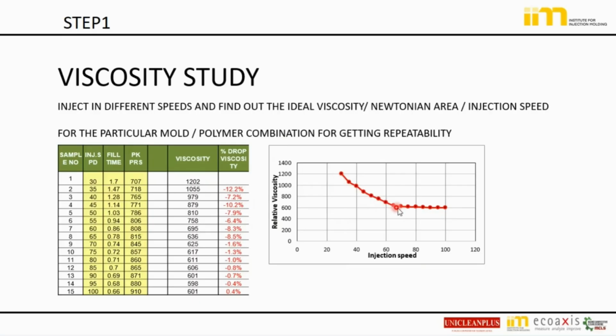And the beauty is that from 30, 35 and so on, with every different injection speed there is a change in the viscosity. But after 70, you can see it has become flat. This flat area is the Newtonian area. Any minor change in the raw material MFI affects the viscosity. Any change in the atmosphere affects the viscosity. But this is the beautiful spot for any such natural variation: our material, the filling pattern, the way it fills remains the same, because this is a Newtonian area.